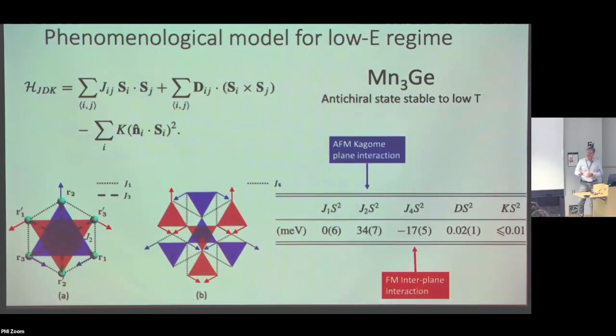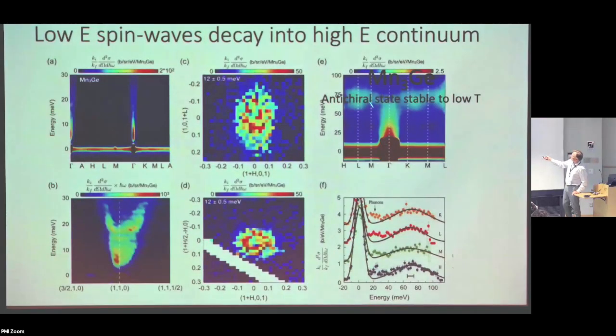And working with our colleague Oleg Chernyshov and his students, they developed a phenomenological description of spin wave excitations in these kinds of triangular lattice structures that is very interesting in its own right, and they've actually continued in that kind of research. For us, it was very helpful to be able to look at just low energy scattering, because at higher energies, it turns out that there's a lot of damping, you can see it here. We really just have the low energy part of the excitation, but at high energies, everything is damped because of the electron hole pair excitations, because it is a metal with quite high electron density.